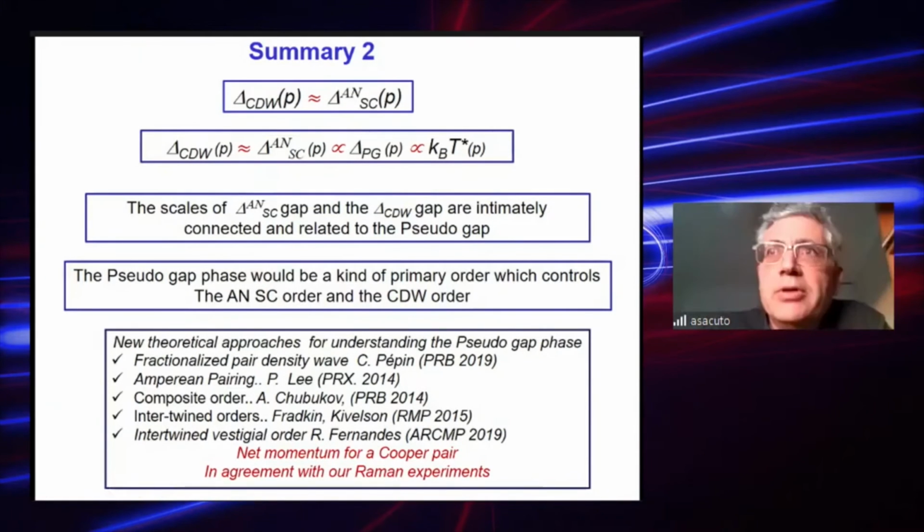The point is that, as mentioned previously, we have to find the good way to detect the charge density wave, and especially the energy of the charge density wave, because the effect of the pseudogap is huge and destroys all the quasi-particles along the principal axis of the momentum. So if you want to detect the charge density wave, you have to go a little bit away from the antinodal region. This is the reason why we are looking in the nodal region to detect it.